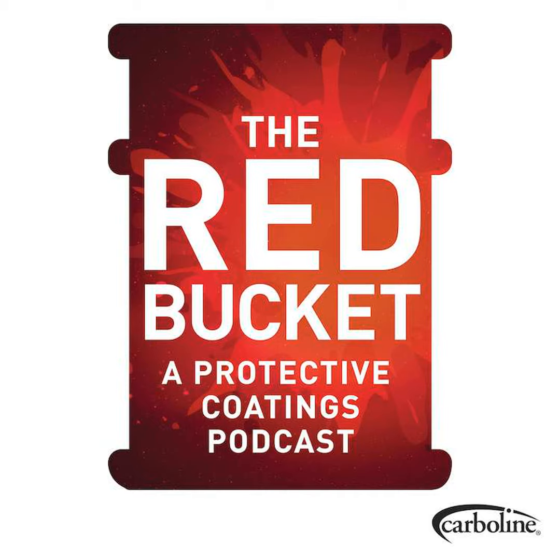And so that may only require you to work one night or two nights if it's a secondary containment area to get it primed. Because the other thing you have to keep in mind is that no one covers the surface 100%. Right. The effective bond area probably at best will be 92 to 94%, even with a very efficient crew. And so you still have the potential for outgassing. And outgassing is generally when the concrete is warming. There's a thing called off-gassing, when there's something going on below the surface that may be due to the concrete having impurities in it, like AAR or ASR, where the moisture is being consumed and it keeps reacting. So there are many things that we can't give an empirical answer to as much as we'd like to. Right.